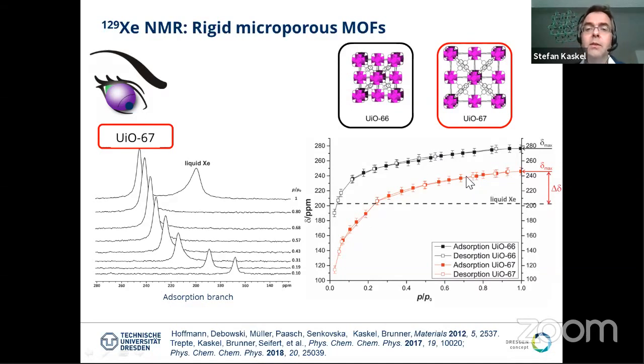And you can already see the impact of the pore size, because in the UiO-66 you have the smaller pore size, and therefore the chemical shift in general is further away from the pure liquid behavior. So if you have a huge pore where basically the atom only sees other atoms, then it would be closer to the liquid xenon behavior. And once you have more surface interactions, you're moving up here and you're showing a different chemical shift, but you also have the pressure dependence. So this is the rigid material.